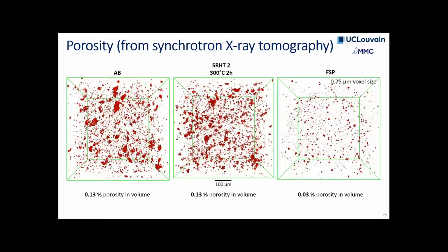If you look at the porosity in these materials, you can see that as-built, stress relief heat treatment 2 and FSP, well, these ones have very similar porosity levels, while the hot isostatic pressing one has a very significant drop in porosity, 0.03% compared to 0.13. But more interestingly, these large ones are just gone here. So you don't have them anymore. You don't have large porosities. So that made us think that this would have a very significant impact on the fatigue life.